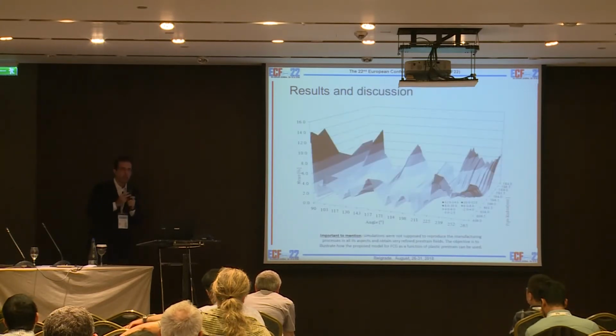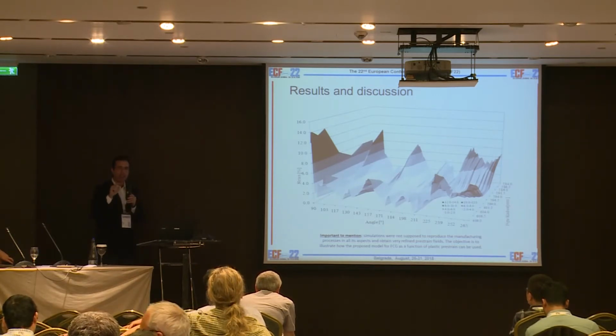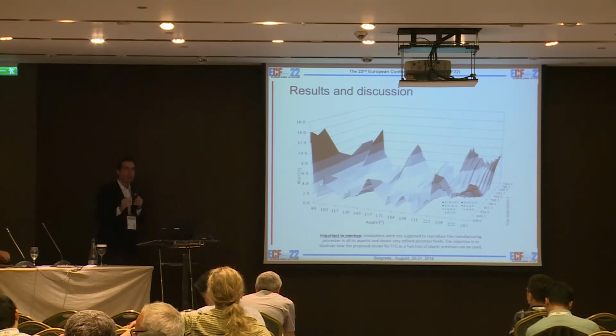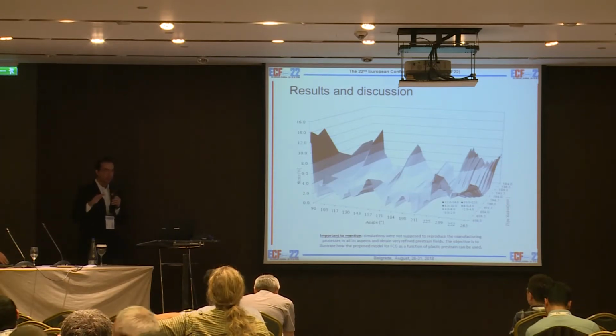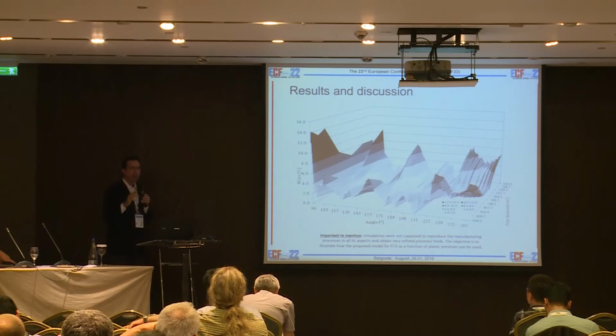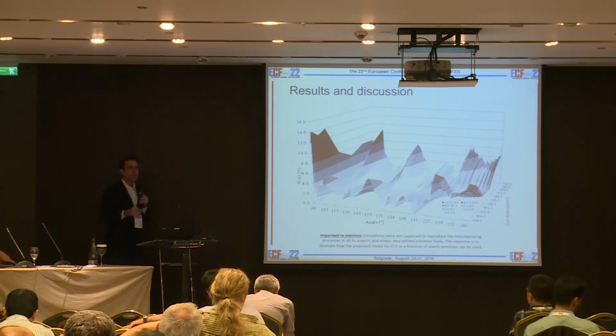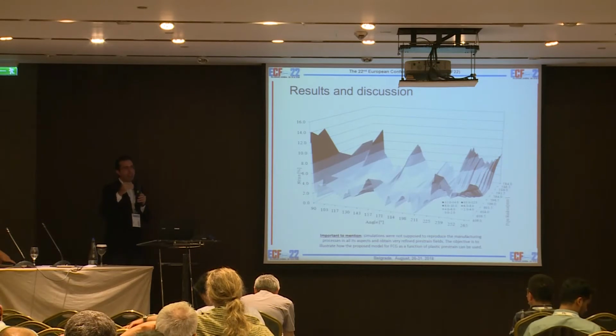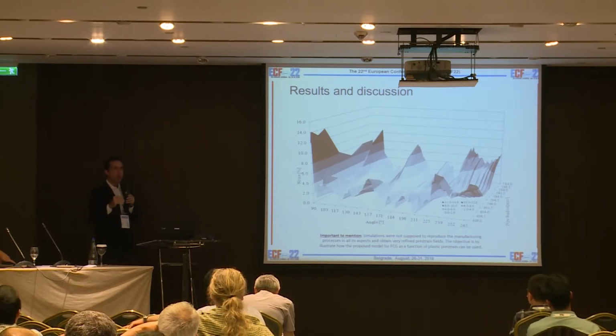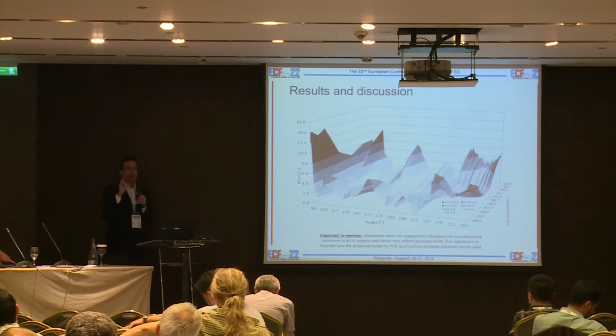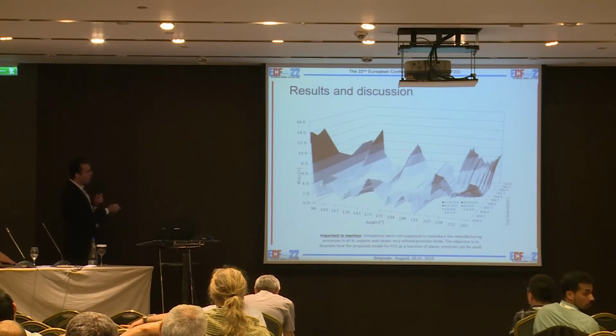In terms of the prestrain distribution, I will call attention to something that is important here. These simulations for the ASTM A36 were not supposed to precisely describe the strain field, so it's not so smooth. For the API 5L applications, we used more steps and a more refined mesh to obtain the plastic strain fields, both for UOE and for calendaring. So I recommend it is done for every application you need. Here, the trends are the same, but the graphs are not so smooth as they could be.